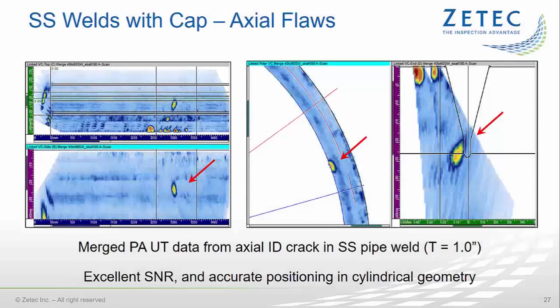My next slide shows the phased array images obtained with this probe configuration on an actual crack in the considered pipe weld. The images shown are merged data from all focal laws. On the right side of the slide, we can see the end view. It shows that the applied group of skewed focal laws in combination with a two-line inspection sequence allows to fully cover the examination volume on one side of the weld.